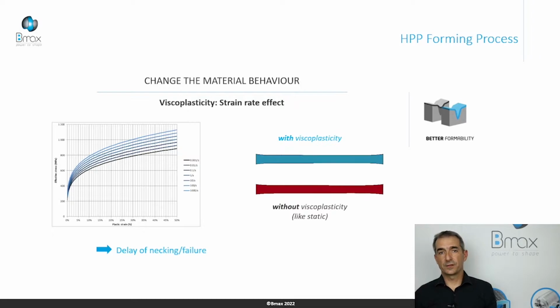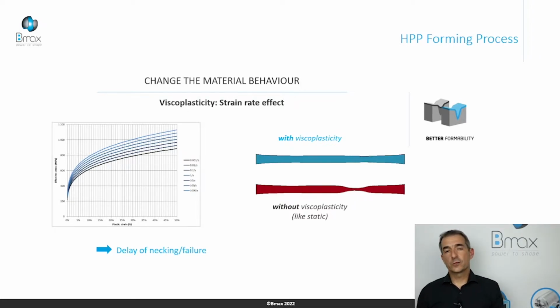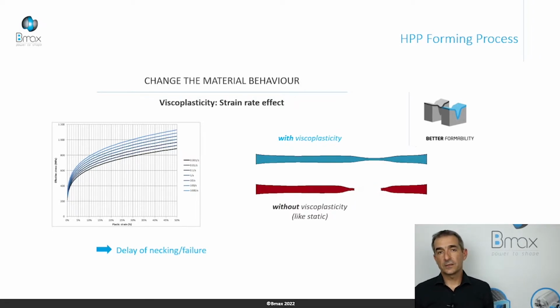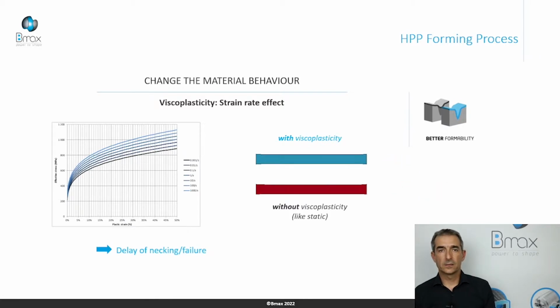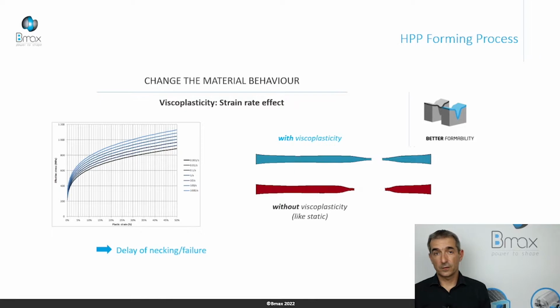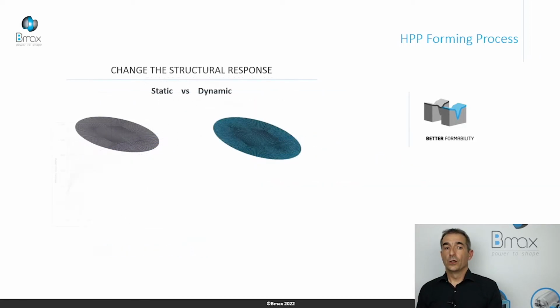As you can see, with a very small viscoplasticity effect on the right, in just a simple tensile test, we can delay the crack on this sample. So viscoplasticity can enhance the formability. It's the first effect of the dynamic loading. The second is to change the structural response.